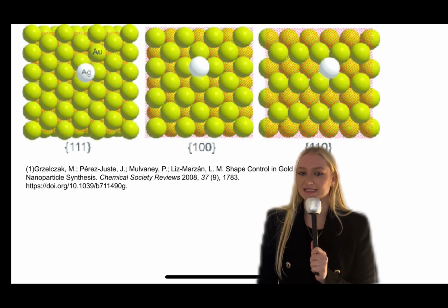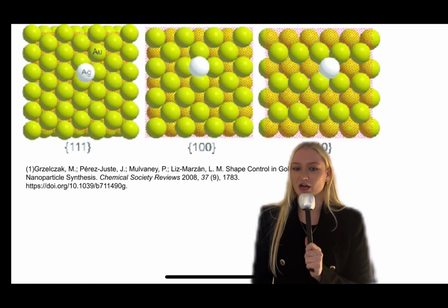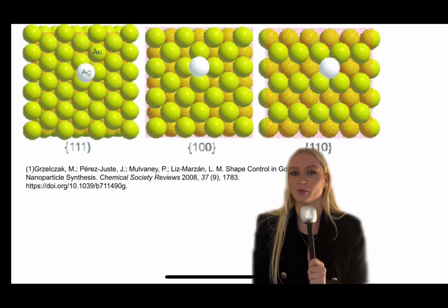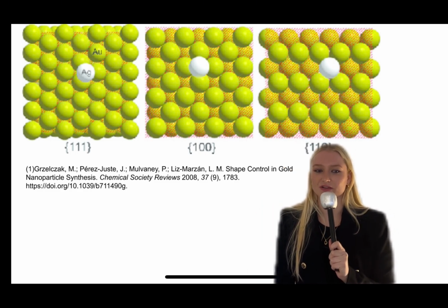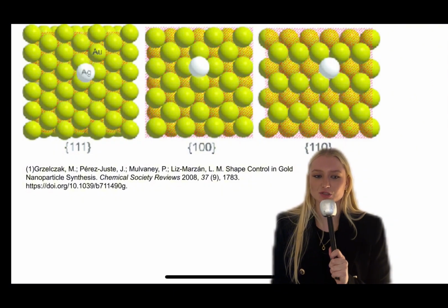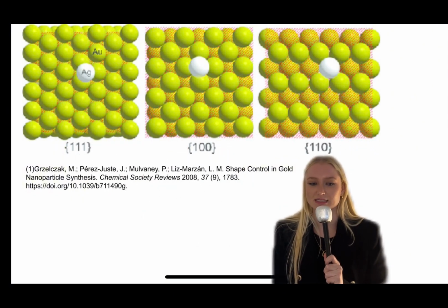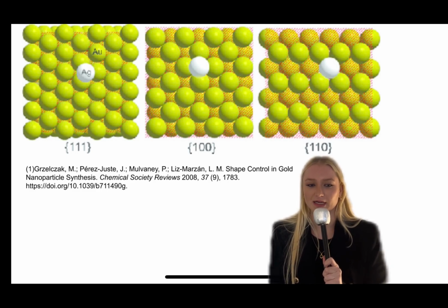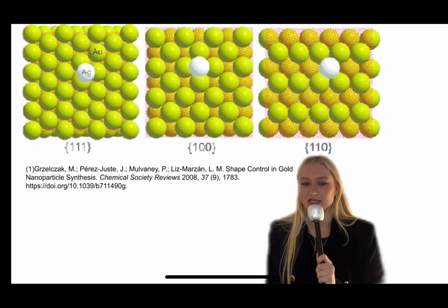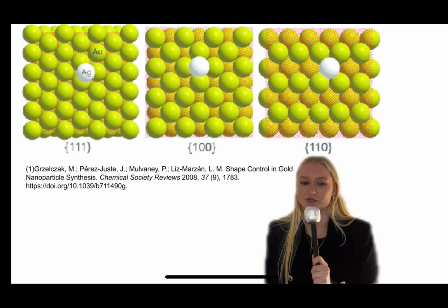of a monolayer that can stabilize surface facets of differing energies depending on the ratio of metal ion to neutral metal. Surface facets are the consequence of a specific packing order of ligands. This is described by a bracketed notation that describes the orientation of dominant exposed faces along a particular crystallographic plane. This allows for silver to deposit onto certain sites of a gold nanoparticle surface, which influences the growth rate and